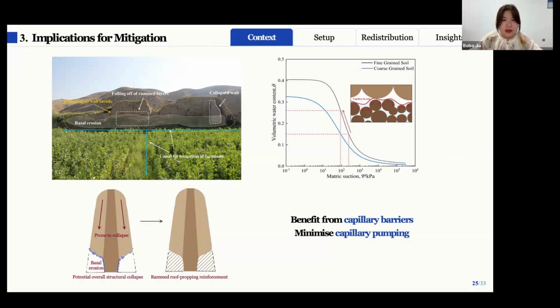So based on this, if the repair soil is designed to be coarser than the original soil, it can act as a capillary barrier. During evaporation, this limits the upward water migration and therefore reduces the transport of dissolved salts. On the other hand, if the repair material is finer, it may enhance capillary pumping and accelerate water and salt movements. So the main idea is to use capillary barriers to limit water and salt transport while avoiding configurations that promote capillary pumping.